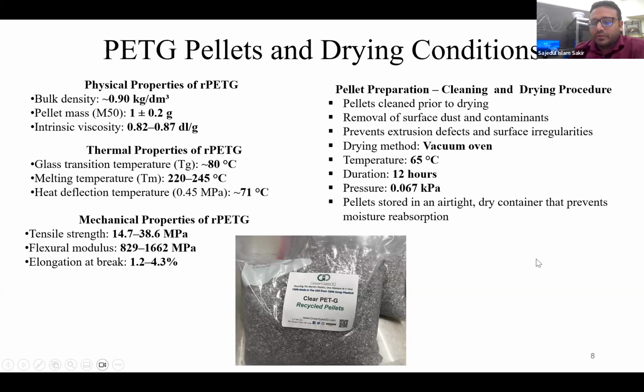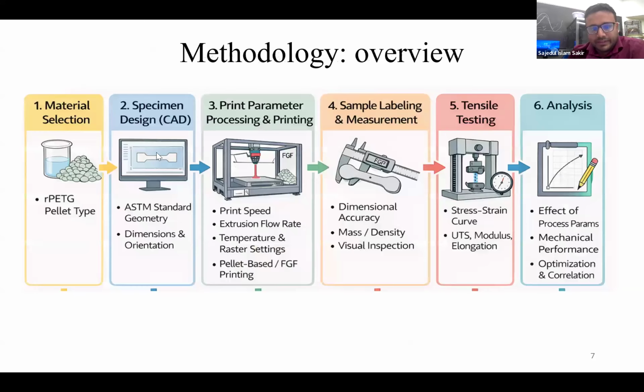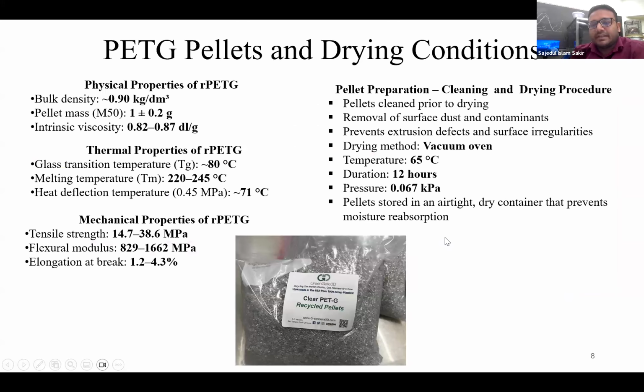And how we prepare before printing. So if you see here, first the PETG, and then we have to go through the printing. So we have to prepare it, and for this, we have to dry it. We are using a vacuum oven. The temperature setting is 65 degrees Celsius, and we are drying it for 12 hours, and the pressure is 0.067 kilopascal. On that setting, we are drying the pellets for the removal of dust and contamination, and to dry the pellets because there is some moisture content in them, so we have to dry them before they go to the hopper of the printer.